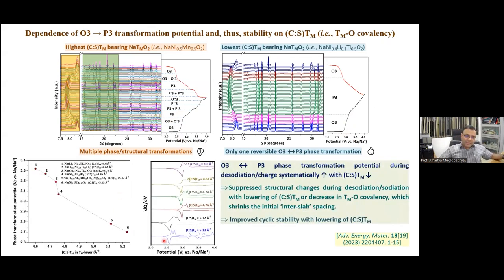Even dQ/dV indicates that as the charge to size ratio is lower, the first structural transformation happens at a higher potential. Because the first structural transformation, that is O3 to P3, happens at a higher potential, there is no room left for the other structural transformations to take place within the potential window used. So that is why this material remains well protected in terms of structural change during the electrochemical cycling. But again, why is it so?